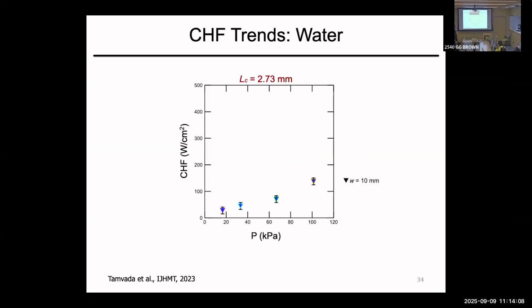So let's do water. Water is 2.73. If you do 10 by 10, that's 10 millimeters by 10 millimeters, you get results consistent with hydrodynamic theory, Zuber. Now reduce one dimension to 2 millimeter, and you get a much, much higher, 4 times higher heat flux. Go to 1 millimeter, no change. Go to 0.5 millimeter, no change. So we realized that once you go below the capillary length, all of a sudden you get a cap. You no longer have a higher heat flux from the surface.